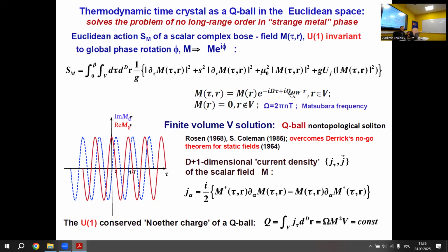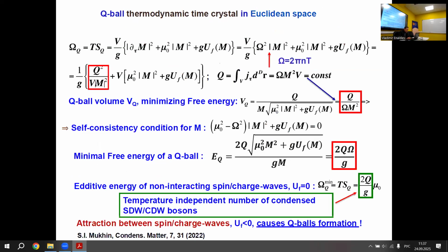So in this theory, everything looks crazy, but I hope it's correct. Usually people would say if you have nesting, you will have charge density wave or spin density wave. No, guys, at high temperatures, you will have Q-ball first. And then it is shown in the second publication, which is also in the list, that the TC of spin density wave transition or charge density wave transition is lower than what I'm telling you about T star, TC, superconducting, and so on. So thank you for this question.